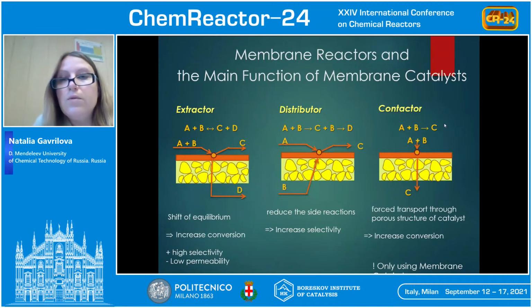If we use a contactor, all the gas mixture goes through the catalytic layer, and under reaction conditions new effects caused by Knudsen diffusion appear. So this mixture can multiply contact the catalytic sites, and it allows a more effective use of catalytic material.